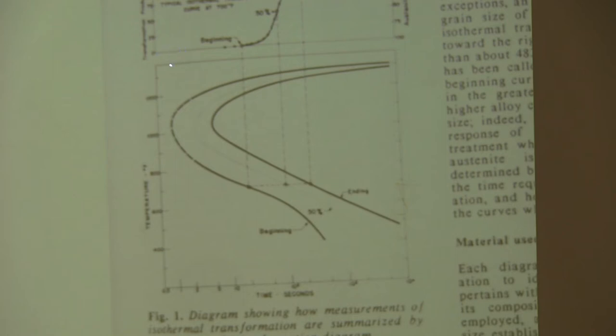What the metallurgists would do is quench a very thin strip into a bath and hold it at some temperature. The bath might be hot lead, at some temperature, and they'd measure the transformation. They really couldn't get things less than about 2 seconds because the thing won't quench that quickly. So that's sort of a dashed line. And this is the beginning of transformation. The 50% line is this very barely visible line here, and the end of the transformation is here,